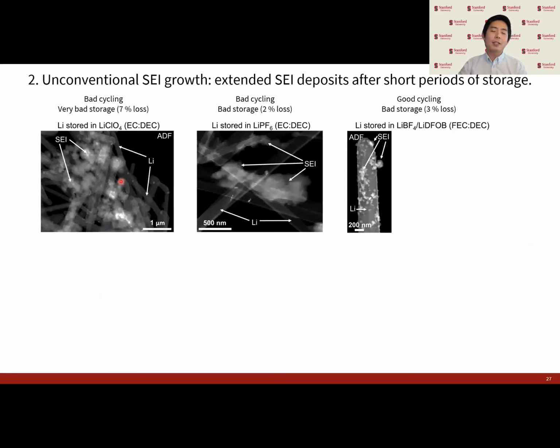But the thickening of that compact SEI isn't really the whole story for lithium metal. So zooming out to capture more of a micron length scale, we start to see deposition of large SEI particles along the lithium surface, which we call extended SEI due to their larger length scale. So the SEI is typically thought of to exist at the 10 nanometer length scale, but here we're seeing hundreds of nanometers of SEI particles.